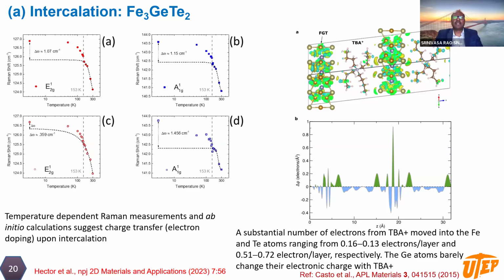From the Raman shift, we computed the spin phonon coupling, and we find that the Raman measurement showed a strong electronic doping effect. These measurements were complemented by theoretical calculations, and the calculations show that a substantial number of electrons from TBA plus moved to nearby FGT layers, for example, about 0.16 to 0.13 electrons per layer for iron. For tellurium it is much higher, 0.51 to 0.7 electron per layer.